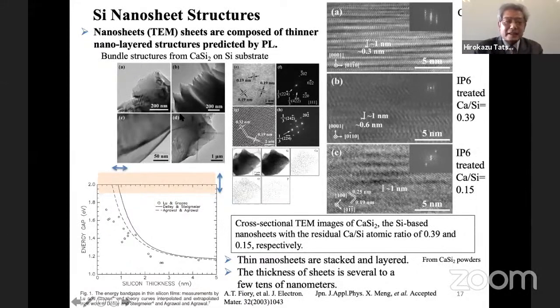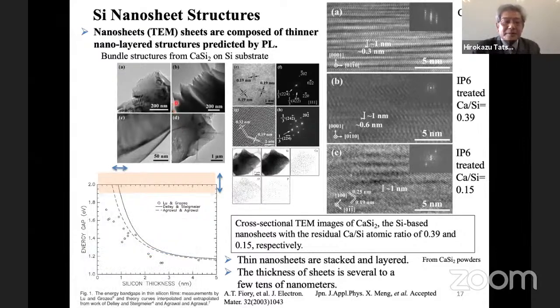So this is a TEM observation of the bundles. Sheets are easily exfoliated from each other to make thinner layers. From structure characterization, it's confirmed to be silicon in very thin layers, because such spots are very special for thin silicon layers.